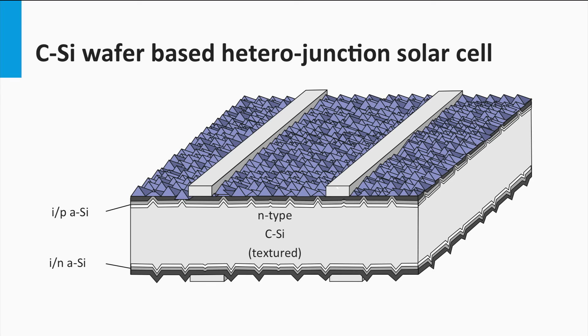The ITO is needed as the conductivity of the P-type layer is too poor. This results in such small diffusion lengths that a practical metal finger spacing cannot be achieved using the P-type layers. Therefore, ITO is used.